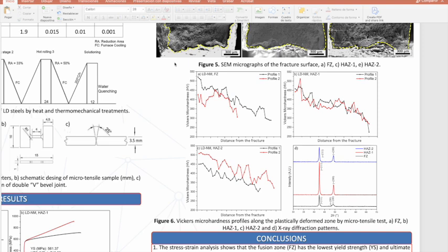From the figures, it is evident that there is a higher hardness in the zone near where the fracture occurs, indicating significant hardening due to the localized plastic deformation during the micro-tensile test. Another important point is the consistency observed among profiles from different samples, suggesting that the conditions were practically identical due to the applied stress in the zone, which increased dislocation density and consequently the hardness of the fracture, regardless of the specific region studied. Once the peak hardness value near the fracture zone is reached, a reduction in hardness was observed as the distance increased.